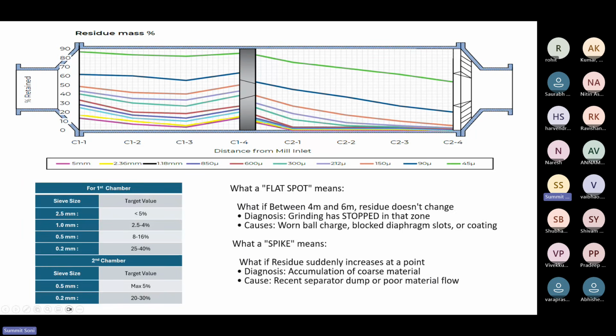What this means is I've got a trend. Let's say I will exclude the graph at 45 micron or 90 micron. Let's do 45. So we will remove all these lines and all the other lines, and we'll just see the green line here. If I take this line, what I can see is it's gradually reducing, but at this end it started increasing, which is not a very good indication.